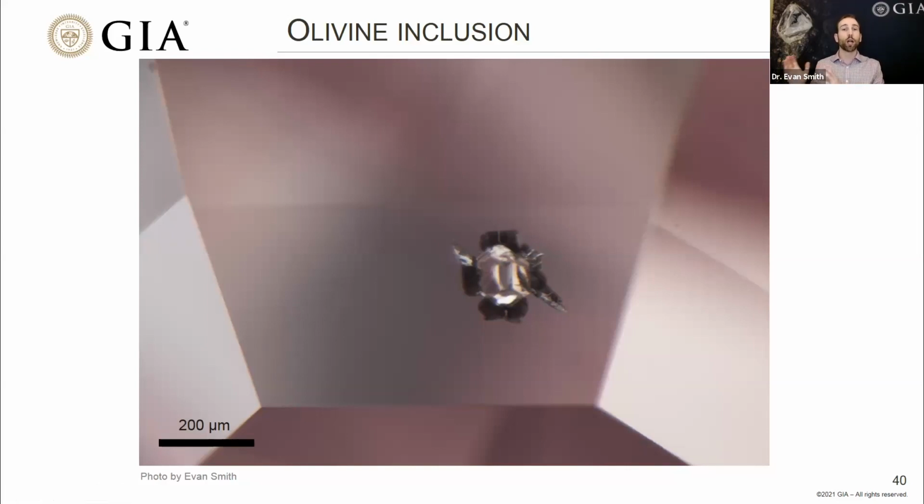The carbon of the diamond has turned to graphite, which is also made of carbon, so it's just changed its polymorph a little bit. It's not that unusual to find black fractures around a variety of different types of inclusions, and quite often that black is graphite. The actual mineral inclusion itself, the volumetric part of it, is the thing here in the middle, this colorless inclusion of olivine.